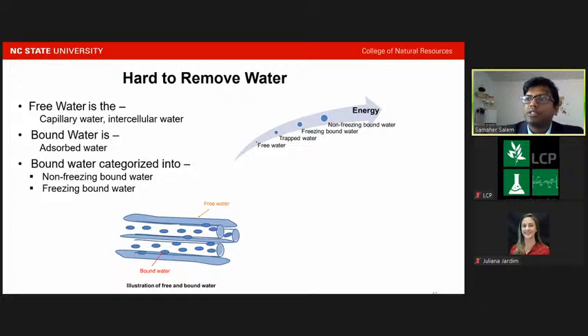The charge difference between the oxygen and hydrogen of cellulose hydroxyl is lower than the corresponding charge difference of the water molecule. And this difference favors the formation of cellulose-water interaction, which consequently leads to cellulose-water hydrogen bond formation. When all the sorption sites are saturated with water molecules, they form clusters through water-water hydrogen bonds, which are weaker than the cellulose-water hydrogen bonds. This gives rise to heterogeneity of water mobility, where the slow-moving water is known as bound water, and the fast-moving water is known as free water.